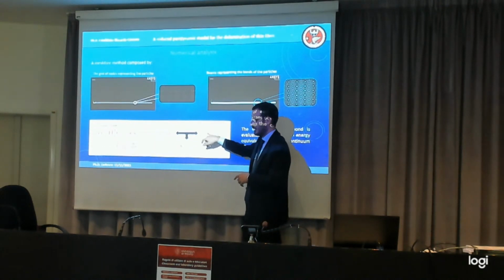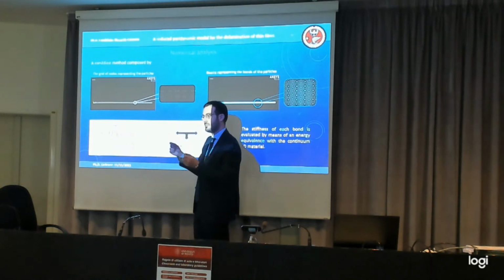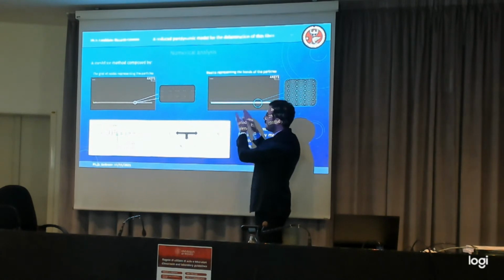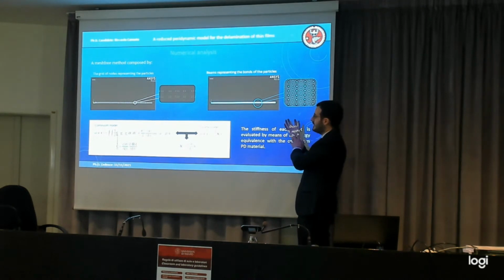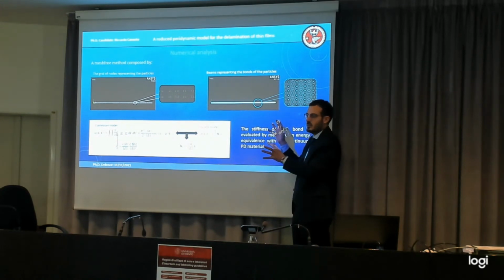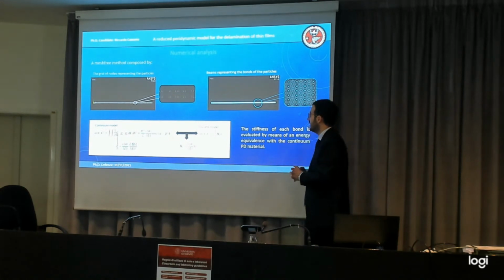And then you compare it with standard local energy, and you see that actually this energy resembles that of a spring truss, so that it can only withstand compression. And so it is possible to imagine the non-local continuum as just a local model. The numerical model is a local one, where you have nodes connected with standard local beams. But these beams are connecting faraway nodes in an hyperstatic way, and that is where you retrieve the non-local behavior. And this is how you build up the...